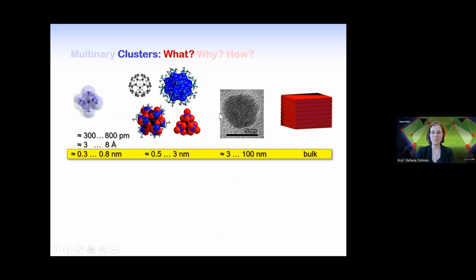If you look at this slide, you will see that there is a difference in general size. So they overlap at some point. Because of the number of atoms being involved, there's a size regime between half a nanometer and 3 nanometers that has been reported for cluster molecules. And then you would probably go further with the nanoparticles. The reason for this regime is that for bigger molecules, you will get into a situation where the atoms are no longer defined. So you will have a lot of disorder. They get more and more ill-defined. And this is then the point where we would speak rather about nanoparticles.